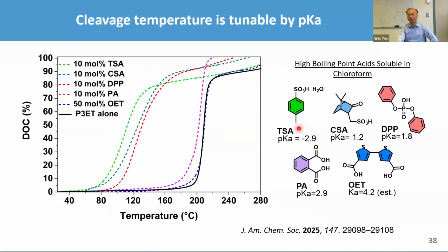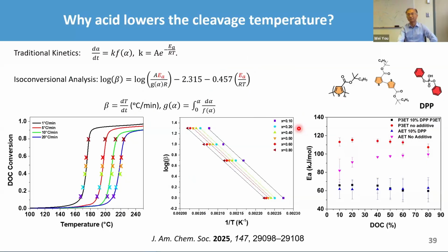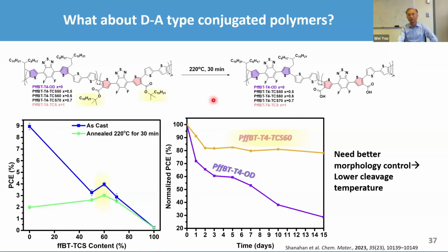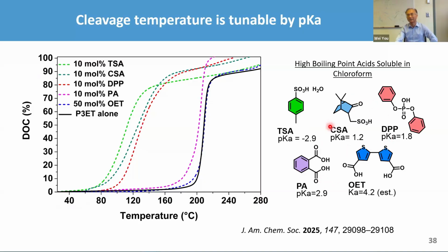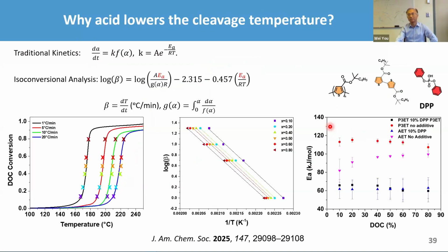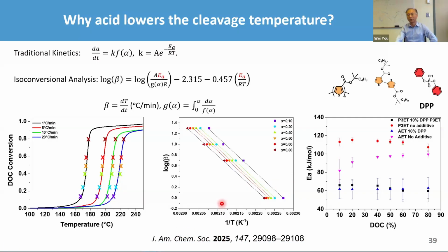Very recently, we came up with an approach looking at the acid impact. Sorry about that, I can't even go back now. Oh yeah, I'm coming back. So we were able to look at the pKa of the acid. We realized that this acid cleavage depends upon the acid you're using. If you care, you can read this paper we published about a year ago. We derived the equation, showing that by using the acid, you can reduce the activation energy of the side chain cleavage from about 120 kilojoules per mole to almost 65 kilojoules per mole. So that means you have a very good way. This is fundamentally why applying acid is able to reduce the temperature you use to do the cleavage.